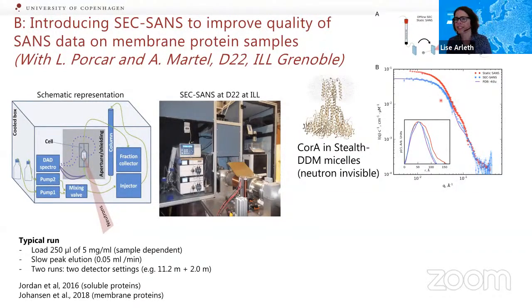So this plot over here shows that there's an important gain of doing this online SEC-SANS purification as compared to the offline SEC static SANS that we used to do. The original approach was that one of the scientists from my group would prepare the samples, then they would run down to the beamline and start the instrument and start measuring. And in the other approach, we purify directly and inject it directly on the instrument.